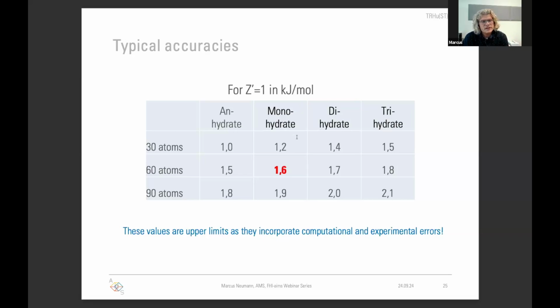It has to be said that this is a sort of upper error for the prediction, for the calculation, because this is a combined experimental and computational error. And sometimes some of the data is not very accurate. For instance, for hydrate-anhydrate phase transitions in the data, there is a lot of hysteresis. So you do not always know at which relative humidity the phase transition actually takes place exactly. Good.